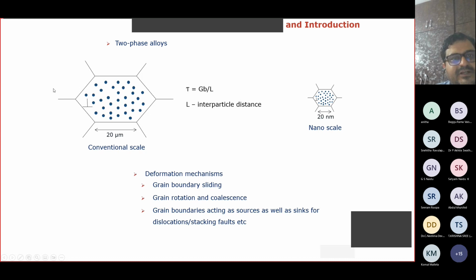And in conventional materials where the average grain size is about 20 micrometers or more, the mechanics are well understood using something called Orowan dynamics. Orowan was the man who elucidated the dynamics behind this type of materials. But the moment you decrease the grain size from 20 micrometers to 20 nanometers, so you have a change in the grain size by 3 orders of magnitude, and you also have smaller precipitates of less than 100 nanometer size, then you cannot extend the dynamics that you have seen in conventional coarse grain materials to a nanostructured